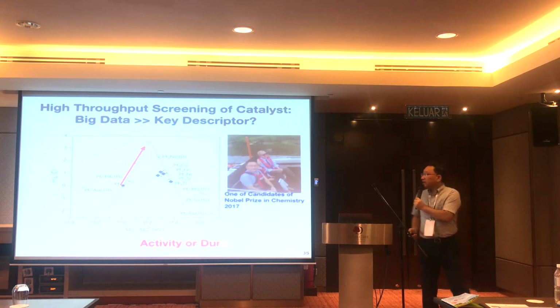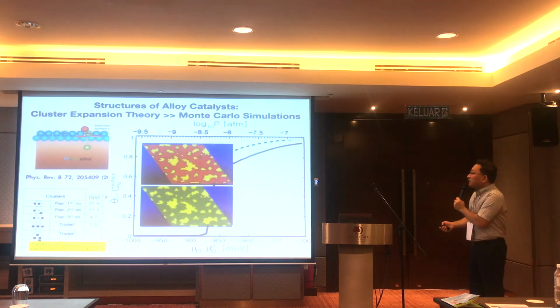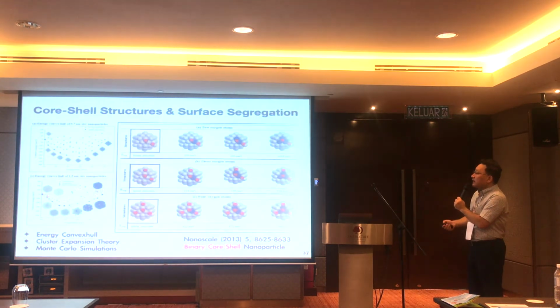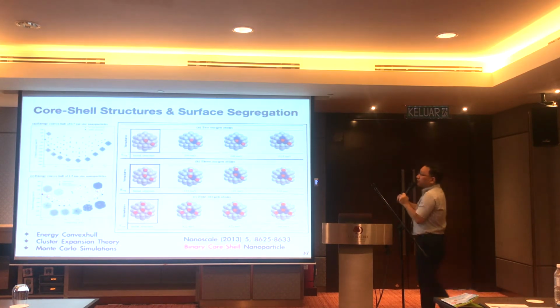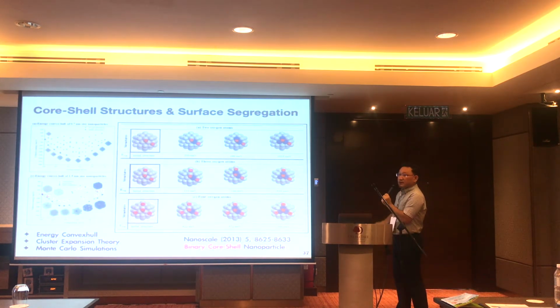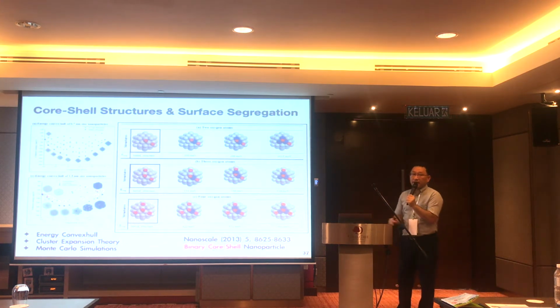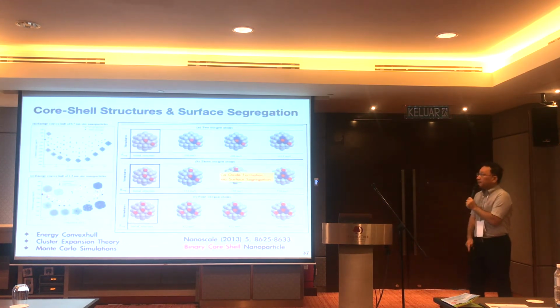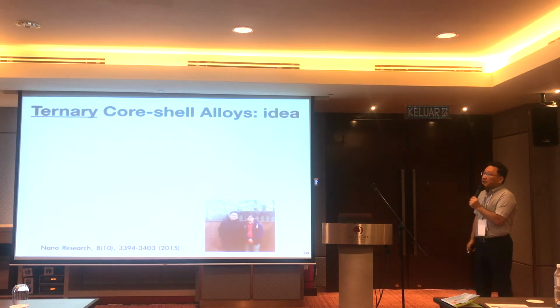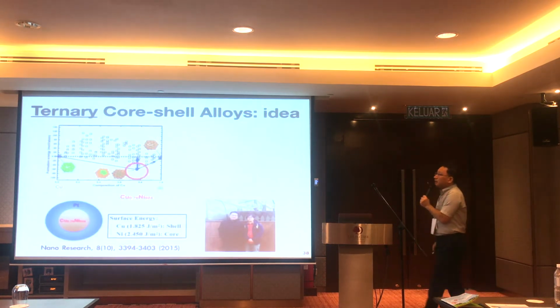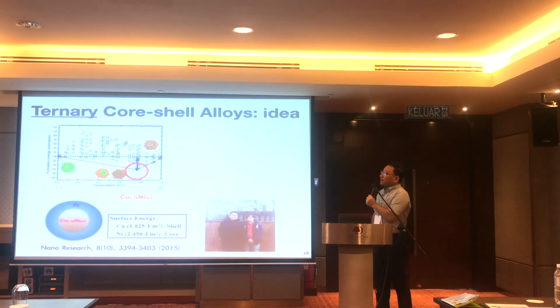The problem is that once you synthesize these materials and put them in the oxidation environment, all the core metal comes up to the surface if there is oxygen adsorption. To reduce oxygen, you need adsorption of oxygen. That's inevitable. But then the core material came up to the surface. That completely killed your materials, right? Activity is not the issue, but they just killed the catalyst materials, right? So we try to develop a better material.